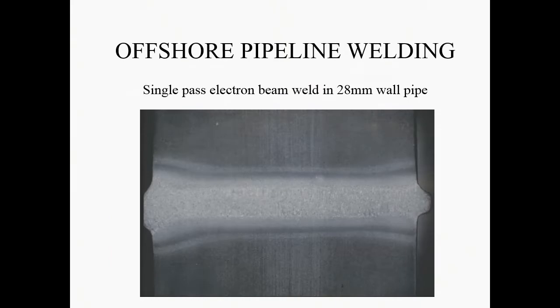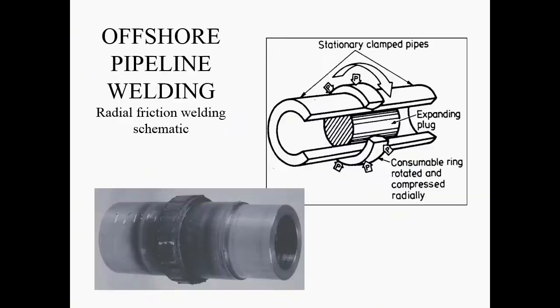What we have next, the aspect of the weld using just one shot, so a single pass, in a 28 millimeter wall pipe. It looks very good, it's a sound weld, but actually applying this in the field is more complicated.